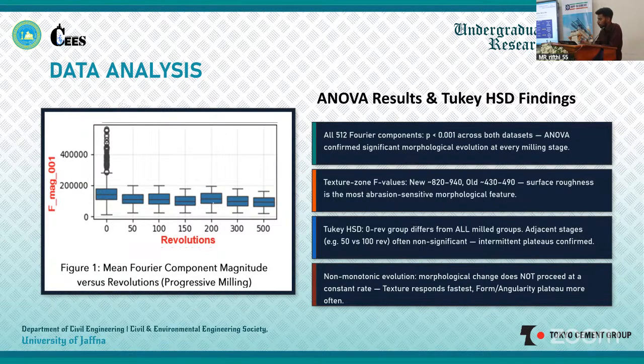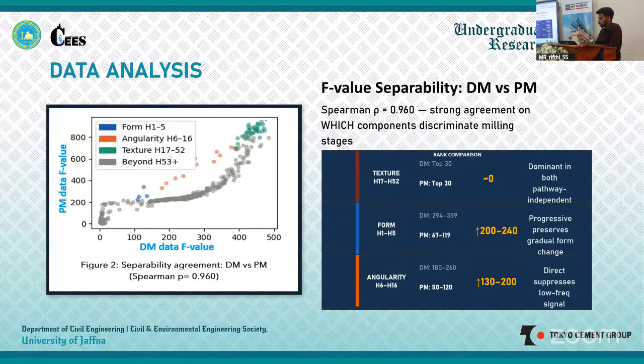One of the most important findings is the correlation of 0.96. This indicates very strong agreement between the progressive and direct milling regarding which Fourier components best distinguish the milling stage. However, form and angularity components rank much higher in progressive milling. This means progressive milling preserves gradual shape changes that direct milling tends to suppress.